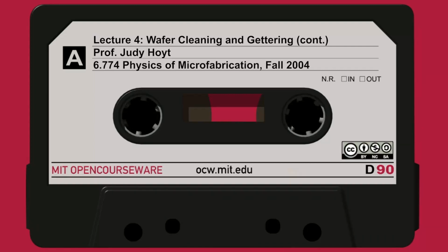And so as it turns out now, instead of 21 particles, this wafer now has 1,012 or so, quite a few. Most of them added in the very small range. Notice they're quite small particles. Most of these are below 0.2 to 0.4 microns or so in diameter. They are perhaps the most difficult to remove of all things. At the atomic level, we're removing copper, iron, sodium. We can do that, but particles have a certain mass to them. And they also tend to get stuck. They're electrostatically attracted because they can be charged. They're attracted to the wafer. So it's a little bit trickier to get particles off, and people are always working on new particle reduction technologies.